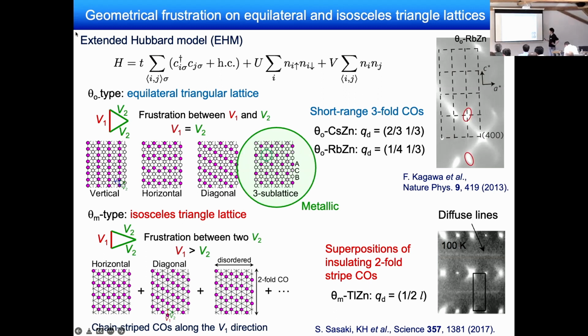And indeed, diffuse X-ray measurements have reported that there is some short-range threefold charge order in both the theta-cesium zinc and rubidium zinc compounds. In contrast, when V1 is larger than V2, which is the case of the theta-M type system, the ground state has many chain stripe charge orders along the V1 direction, which include horizontal, diagonal, and disordered states along the V2 direction. And indeed, in the theta-M type compounds, diffuse lines corresponding to the superpositions of the insulating 2-fold stripe charge order have been observed.